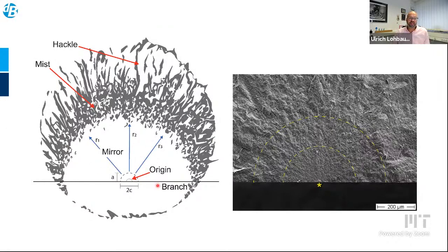It's not always that easy to see such a fracture origin in coarse grained ceramics, for example. It is more difficult, and needs a bit of training and also a bit of distance to the object. We can also see the limitations or the borders of the fracture mirror. And at some point, we can identify different fracture mirrors, which give us an indication of fatigue degradation going on, crack extension going on. So this type of examination is also very valid for investigations on degradation or fatigue failures.